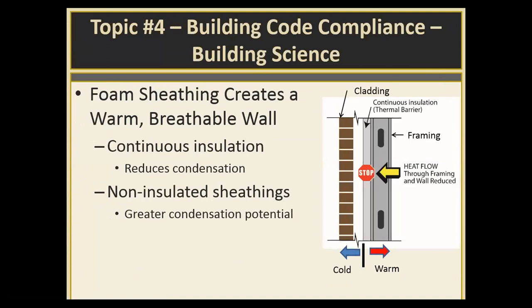From a building science standpoint, I mentioned some of the building science consultants out there that talk about taking all the insulation to the outside. Really what they're trying to do is create a warm, breathable wall. Take the moisture and thermal and all that to the exterior side. Continuous insulation, because the closed cell formulation and the thermal resistance it provides can significantly reduce condensation potential. Whereas non-insulated sheathings don't do that, and you can have the back of the sheathing being cold, and you've got the warm air in a heating environment from the interior that meets on the back side of the sheathing and creates condensation potential, which can be really bad in the stud cavity.